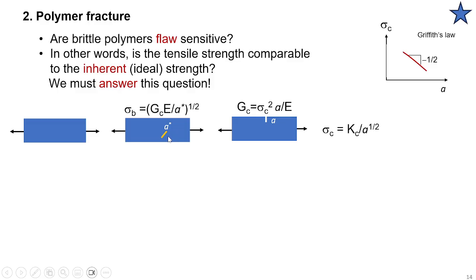Therefore, as anyone doing fracture mechanics would, we make a cut and we examine at what stress the crack will propagate. And indeed, you'll find that the crack will propagate at a lower stress if the cut is larger. So it goes as 1 over the square root of a. If you make a plot, you find that as I use a larger crack, the propagation will occur at a lower load. And people were patient enough to use smaller and smaller cuts, and find that eventually, when the cut is small enough, your material is as strong as without having any intentional cut.